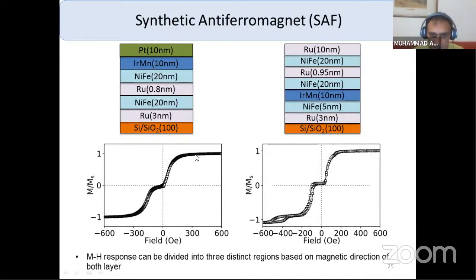Here you can see a saturation region where the Zeeman energy dominates over the spin flop and antiferromagnetic coupling energy. You can see this is an antiferromagnetically coupled region, spin flop region, similarly spin flop region and saturation region. A similar explanation can be made for this system here, but this loop is due to this seed layer, which does not have any effect on the properties of the synthetic antiferromagnet.